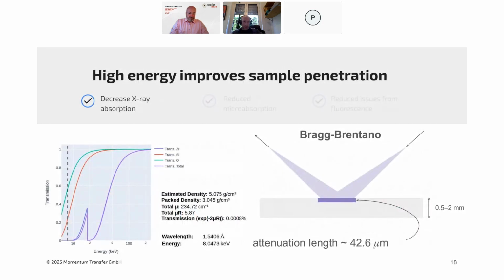So now I want to talk a little bit about the high energy aspect. High energy is great because this actually makes the X-rays much more penetrating of any samples that we put into the beam. So it significantly decreases the probability of absorption. As an example, and I'll show how this works for typical setups in the lab versus ours, I take zirconium silicate here. And what I've calculated is the transmission of each of the elements as a function of X-ray energy. Basically the way that it works is, as you go higher in energy, your transmission should go up,